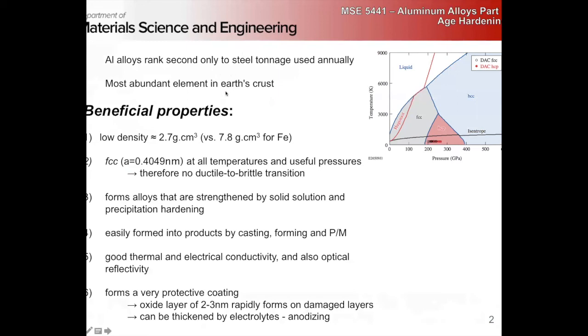If you look at the Ellingham diagram and the electrochemistry potentials for aluminum, it's clear. However, it does form a really nice protective oxide coating, which for a lot of our purposes is a very good protection against corrosion. Unfortunately, we'll find most of the alloying elements that give us good precipitation properties also destroy our corrosion properties. So aluminum copper 2000 series alloys, absolutely horrible in corrosion. Right? We're putting beautiful galvanic couples into our material.